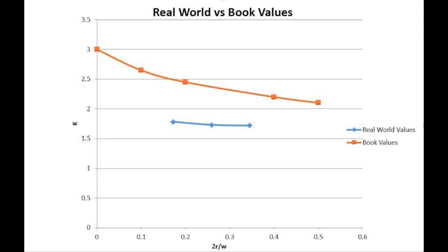As you can see, our calculated K values do not match exactly with the graph in the book. However, the K values do decrease as the radius increases. This may be due to the rate at which we pulled apart our specimens. We came to understand when using an Instron device, this variable can change the results radically.